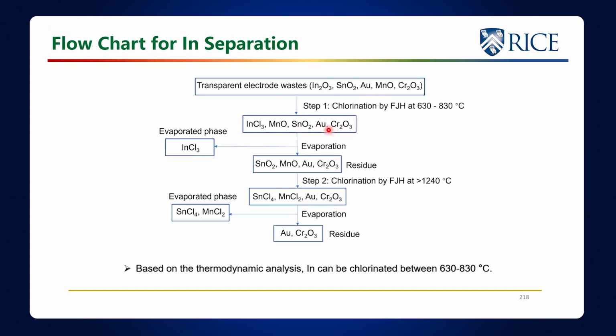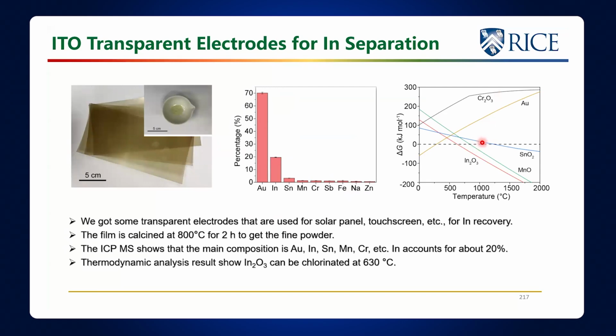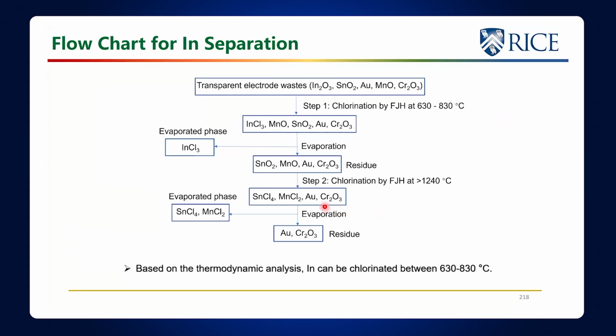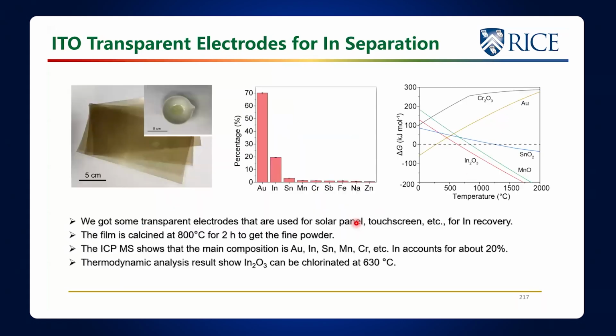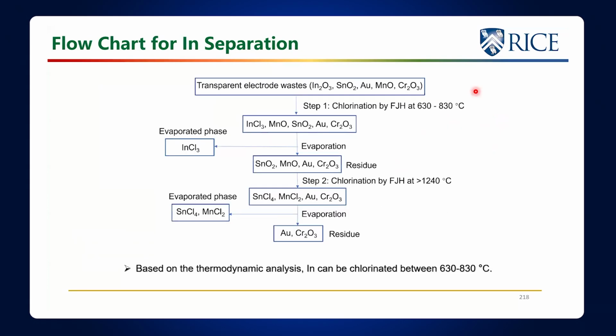The gold would remain as the gold metal. And then as soon as that indium chloride forms, we should be at a temperature where it would immediately distill out. Then you could take this residue and do the chlorination at over 1240. So remember, if you go over 1240, up in here, you should get all of those other ones, so they will form the chlorides. It turns out the chromium doesn't, because you see, chromium never goes less than 0. So the gold remains as gold metal, the chromium remains as chromium oxide, and here you distill out the tin chloride and the manganese chloride, and you're left with this in the residue.